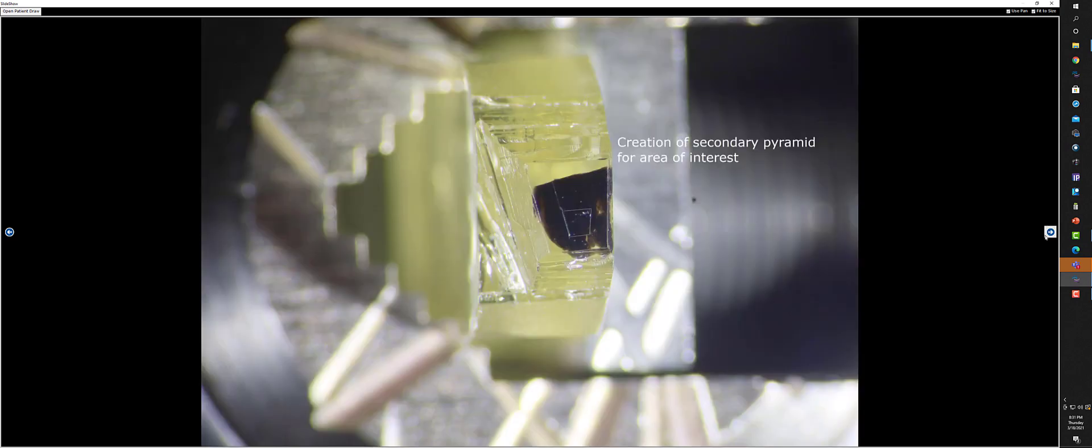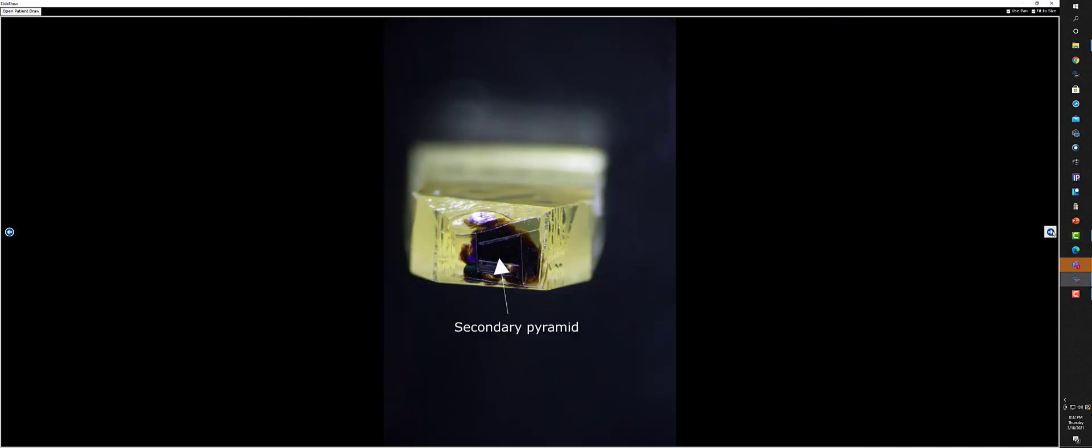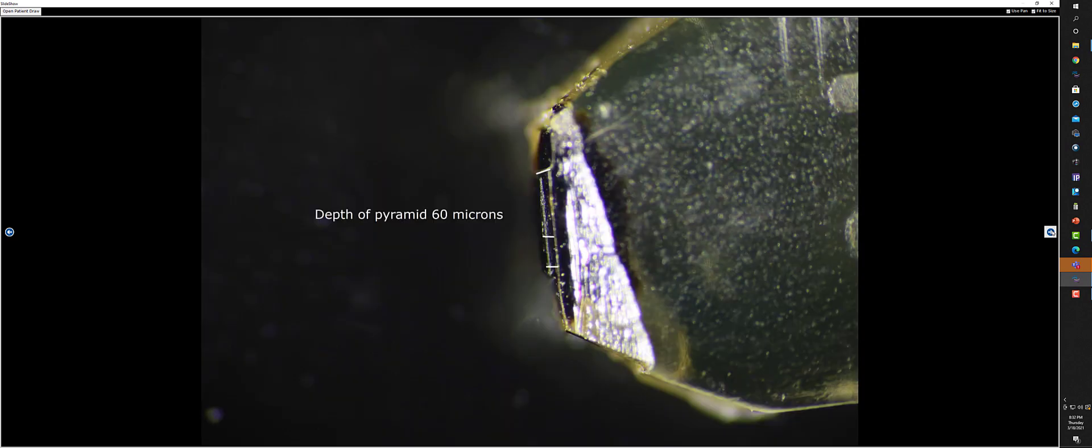You have to build a pyramid on top of the big pyramid, and that pyramid should only be about 60 microns thick. You can cut the whole specimen away, but then you waste it. So I like to create this pyramid sitting on top of the larger pyramid, and that has to be done very carefully. Here we are, we use a special knife to do that. There's the secondary pyramid cut into the surface of the main pyramid, and the depth is about 60 microns thick, sitting on top of the plane of the major pyramid.